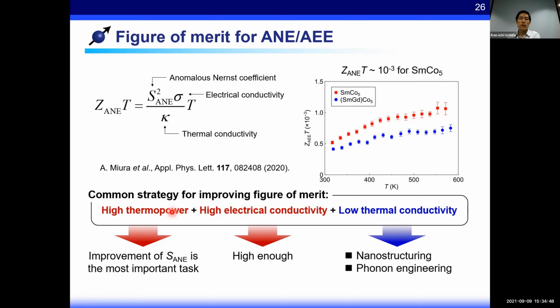Many researchers are looking for new materials and principles to further enhance the transverse thermal power, and reduction of thermal conductivity by nanostructuring or phonon engineering is also an important task, although such activity is quite limited. For example, if the transverse thermal power is enhanced by 10 times from the current record high, and the thermal conductivity is reduced by half, the figure of merit can be greater than 0.1. This value is still very small. However, owing to the aforementioned unique functionalities, I believe that the transverse thermoelectric conversion with such improvement leads to various applications.